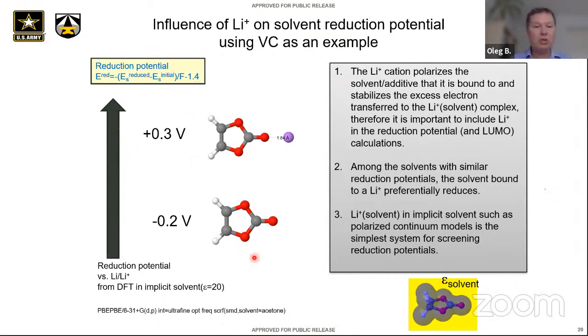First question is, what should we screen? If you screen something like VC and calculate the reduction potential versus lithium, you get a negative potential, which means it's going to be stable. Clearly, it's very important to have lithium around, because if you have lithium next to the solvent molecule and you give an electron, the electron gets stabilized because lithium polarizes the solvent. Without any reactivity, I mean, without any decomposition or breaking bonds, that reduction potential already gets increased by 0.5, getting to 0.3.